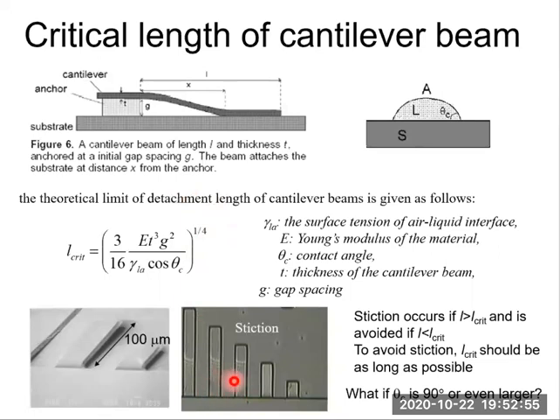And in this micrograph, we can observe that the two short cantilevers are freestanding. And the three longer ones have stiction. They adhere to the substrate, and we can tell the stiction from the color change and also the Newton rings. The Newton rings are caused by the interference of light. And the left figure is an SEM image. We can clearly see that the two short ones are freestanding. The third, longer one has stiction. This one adheres to the substrate.